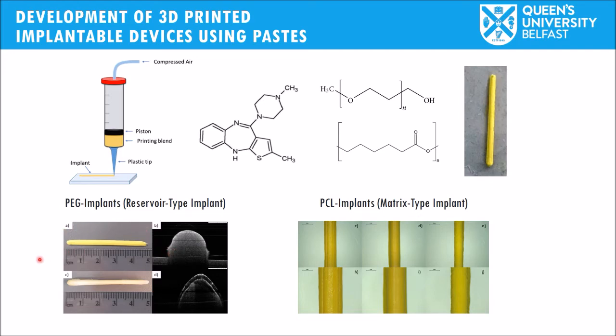In this case we have a membrane. The membranes that we developed previously, we use them again, but before using the membrane, we printed an implant containing an antipsychotic drug, olanzapine, and using high molecular weight polyethylene glycol. Technically it's called polyethylene oxide, because in this case the molecular weight was 100,000. Here we have an example of the printed implant, and here you have the implant coated in the film. The implants were not coated as such; basically they were wrapped in the membrane and sealed thermally using some hot clamps. Here you can see an optical coherence tomography image of the implant and the coated implant. Here you can see the coating.